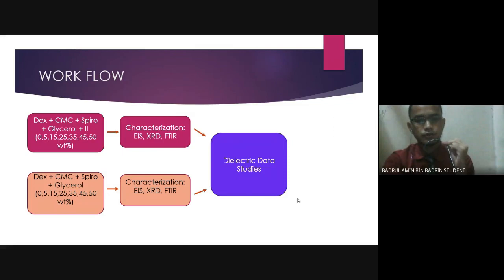So the below flow represents the first system. Dex is for dextrin from starch. CMC is for carboxymethyl cellulose, a carbohydrate derived polymer. So the blend of these two will be introduced with Spiro, the charge carrier donor, and glycerol as a plasticizer, which was found to be a promising candidate to enhance ionic conductivity from the past literature reviews.